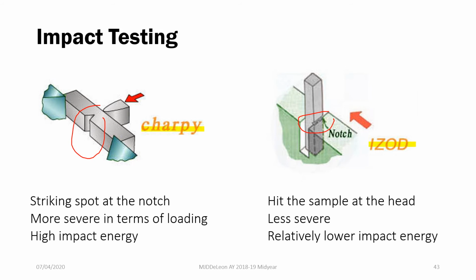Sa Charpy mode, your hammer strikes the material at the point of the notch. So this is more severe. Mas mataas yung impact energy in the Charpy mode. Meanwhile, sa Izod mode natin, yung hammer natin strikes some distance away from the notch. This is less severe. There is relatively lower impact energy in your material. So depending on the type of material, you may employ either the Charpy or the Izod modes. So itong impact testing natin, this will be further discussed in a higher MatE subject.